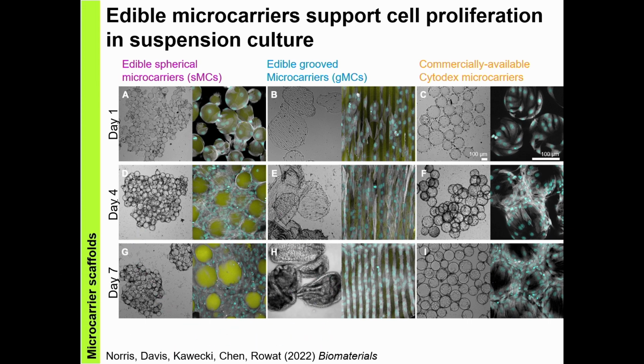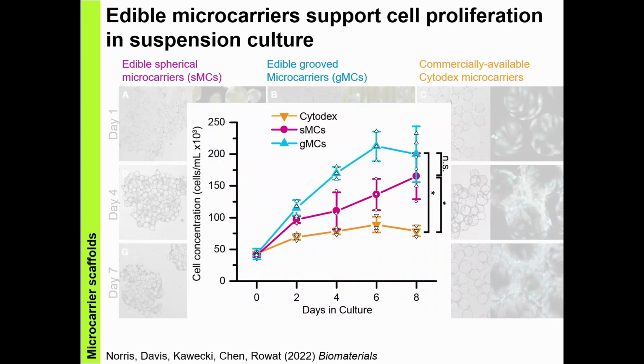It's hard to exactly quantify the cells given these confocal images. So we also conducted genomic DNA analysis to quantify the number of cells over time. And you can see that in all three cases, the cells are indeed growing on these beads in suspension culture, but we do see increased growth for the cells on our grooved microcarriers and the spherical microcarriers compared to the Cytodex. So the microcarriers do seem to be supporting cell growth.